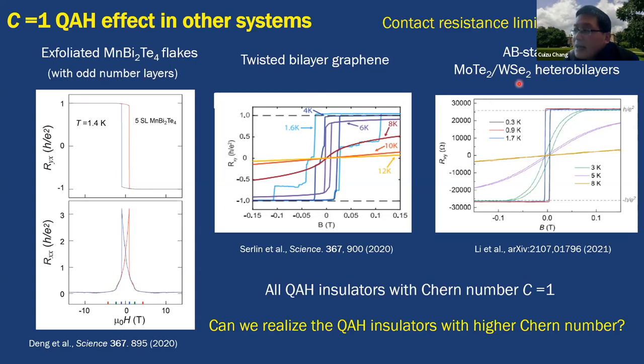More recently, in AB stacked molybdenum telluride and tungsten selenide bilayers, the C equals one quantum anomalous Hall state has also been realized. So in all these systems, the Chern number equals one. Although we say that the chiral edge state is dissipationless, when we take measurements on the quantum anomalous Hall state, we need contacts. If we put on the contact, there will be contact resistance, and the contact resistance is h over C e squared. From this equation, we can see that if we could increase C, we could reduce the contact resistance.